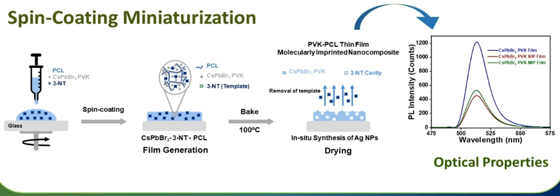The spin coating speed was adjusted accordingly to prepare systematically 150 nanometers thick films. The presence of cesium lead bromide nanoparticles in the polycaprolactone matrix is confirmed by the PL spectrum peaked at 513 nanometers for both references: the NIP sensor, that is the red curve in the graphic, and the molecularly imprinted nanocomposite, which is the green curve